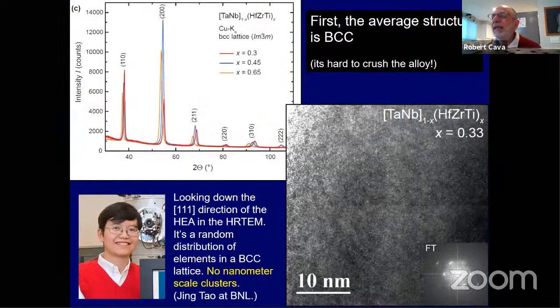An important question is, when you have all these atoms in the pile, why don't they just form some nanoscale precipitates where two of them get together and do something interesting, and the rest of them just sit there? Well, they don't. Here's Jing Tao, who's an electron microscopist at Brookhaven. I made her take a look at these high entropy alloy superconductors, and sure enough, there was no sign of any nanoscale precipitates where two of these atoms have picked themselves out to form a fine scale precipitate in the alloy. So this is a uniformly disordered alloy with 5 elements in it.